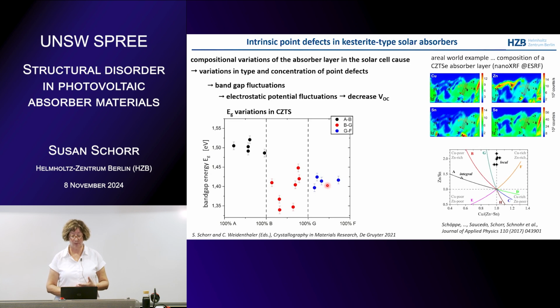To show you a real-world example, this is a CZTSe absorber. This was an absorber from Edgardo from Barcelona, and it was studied by nano-XRF at the European Synchrotron Radiation Facility. And you can see this is for copper, zinc, tin, and selenium, the cross-section and the composition distribution of these elements. And you can see that it's okay, it's already very good, but it's not homogeneous.